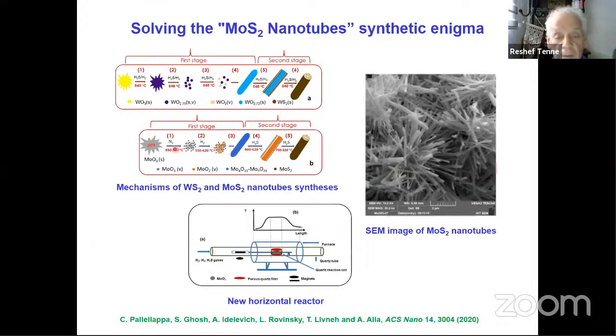She started from molybdenum oxide, and by heating gradually the molybdenum oxide and using larger and larger fluxes of hydrogen sulfide and hydrogen, she could eventually make macroscopic amounts of molybdenum disulfide nanotubes. And this provides a very good material for lots of studies, and we are undertaking now serious studies jointly or by herself.